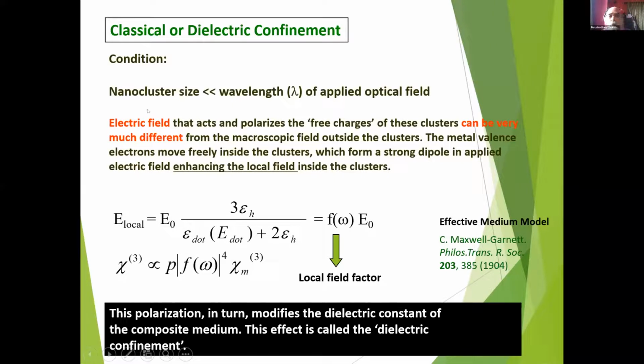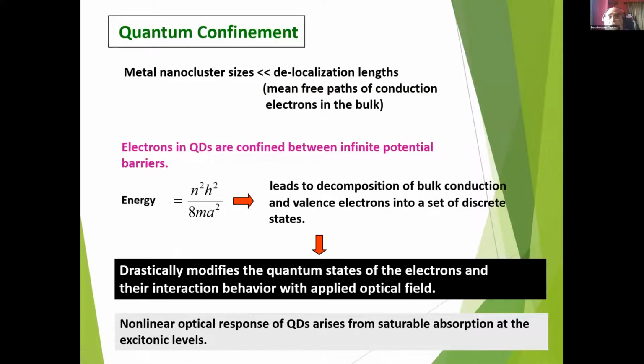In that case, the nanocluster size was much smaller than the wavelength of light. And now, the metal nanocluster size is very small compared to the delocalization length or the mean free path of the conduction band electrons. That gives rise to the decomposition of the bulk conduction bands and valence electrons into a set of discrete energy states, and you know already that the energy is this. So drastically, these two things modify the quantum states of the electrons and their interaction behavior with the applied optical field. These two, the dielectric confinement and the quantum confinement, in combination give rise to the photonic behavior of the metal particles in the glasses.